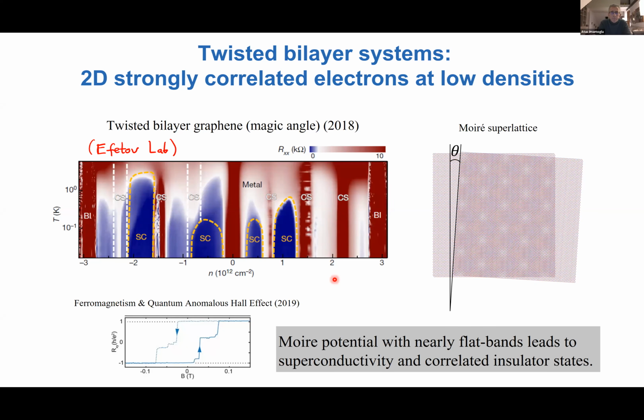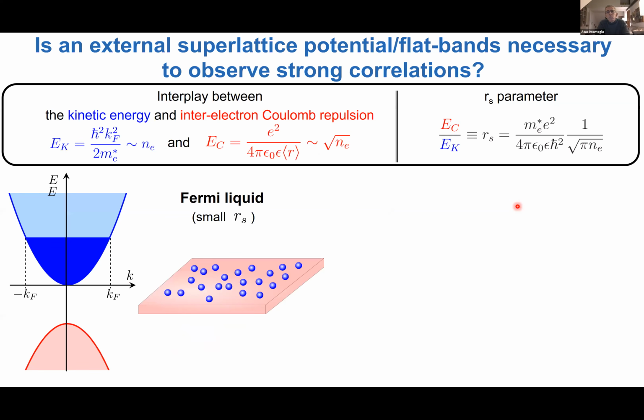in one material. Now, what is really playing a crucial role in magic angle twisted bilayer graphene is the existence of the moire superlattice, which ensures that out of Dirac fermions, one obtains flat bands with very small bandwidth, small compared to the characteristic interaction energy scales. Now, this begs the question whether an external superlattice potential is really necessary to observe strong correlations.